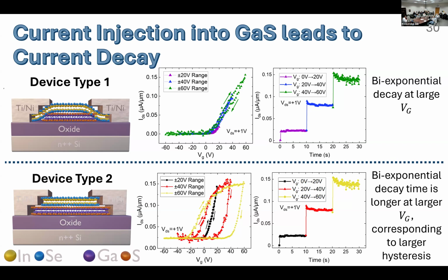So if I follow up with that, you observe hysteresis, which is some kind of thing you don't like, right? Mhm. But you did this experiment pretty slowly, like a few seconds, but our transistors operate at like a gigahertz. Does that mean this will not be an issue if you use it in a CPU and operate it at a very high speed? It can be, if there are no traps that are released in that time scale. But it would be interesting to see if we could do that.